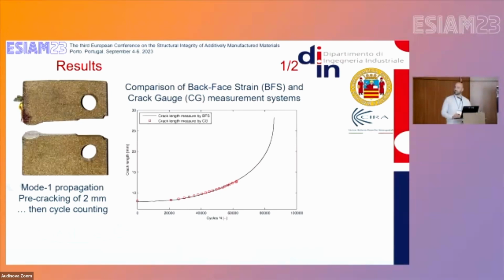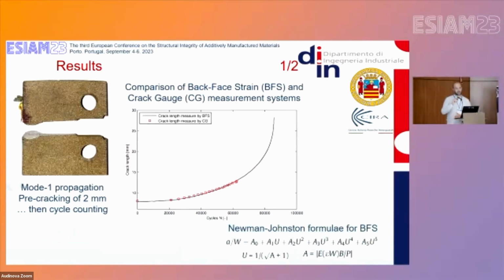We can say that with the back-face strain, as I said before, and through the formula that I reported at the bottom right corner of this slide, starting from the epsilon measured at the back-face, we can derive the actual crack length. So it is a different measurement technique, and we obtained a very good agreement with, let's say, the more traditional measurement system. So, going on